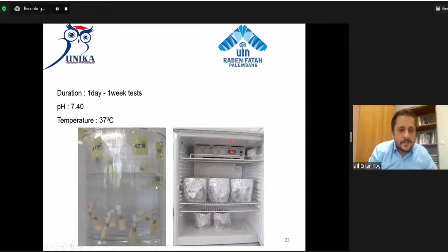And then samples were immersed here in simulated body fluid in a beaker and kept in an incubator which provides nearly 37 degrees Celsius. Test durations are 1 day, 1 week. The test is held here. pH values are also measured periodically, because we have to keep it at 7.4 pH.